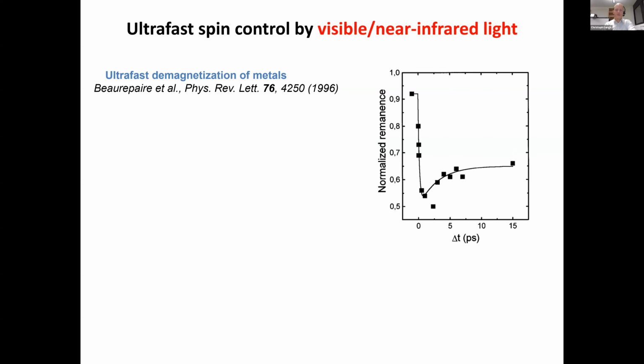And I'll just be brief and wrap up a little bit the history of the field of femtomagnetism, which didn't start in the terahertz range, certainly, but with femtosecond near-infrared pulses. One of the first investigations was by Beaurepaire and Jean-Yves Bigot's group, where a femtosecond near-infrared pulse was used to heat up the spin bath, the spin temperature of nickel, a ferromagnet, on a very short time scale, and thus by destroying the ferromagnetic order, essentially it's possible to destroy the magnetism on a very short time scale, or in other words, a first approach to controlling magnetism on very short time scales.